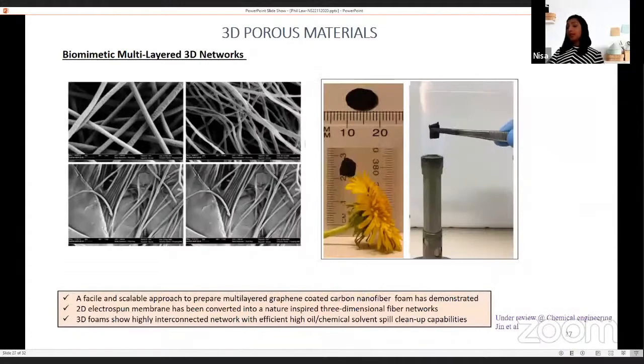So in our current research, we are combining self-assembly approach with adding functionalities. So by using this method, what we are doing is we are converting the two-dimensional carbon materials into three-dimensional forms. So in this particular work, we have used an electrospun mat into a three-dimensional form, and that's the way we found a highly interconnected network of nanofiber features. That's the way we can bring efficient high oil adsorption or chemical adsorption